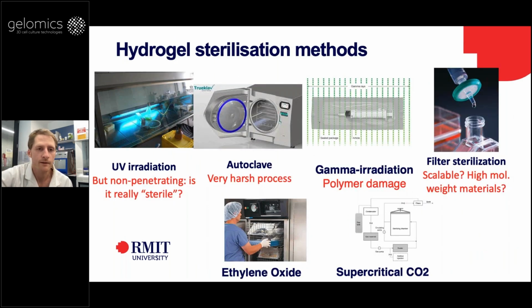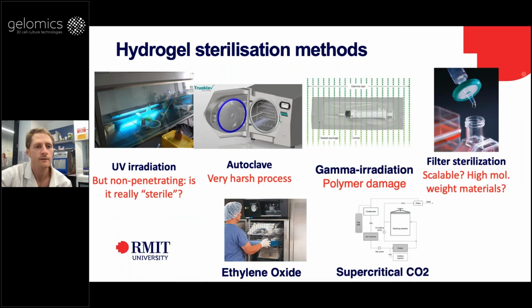We've also looked at sterilization methods. We've assessed various kinds. Everything on this slide we've tested apart from supercritical CO2, which I think is an interesting one. But the big problem is, how do you sterilize large amounts of material? Typically, when people synthesize small amounts in the lab, they might do a filter sterilization, but we want to scale up to multi-kilo batches, and that's not quite possible. And it's also not possible when you've got large molecular weight materials like hyaluronic acid, which might be 1 million Dalton, right?